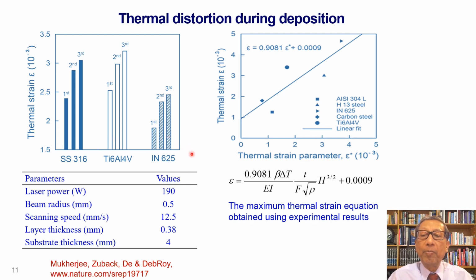It's also very important to validate the model with experimental data so that we can use the model with confidence. And this is what we are doing. We are plotting thermal strain versus the thermal strain parameter which our model gives, and we find that this expression describes the data very accurately for preventing distortion.